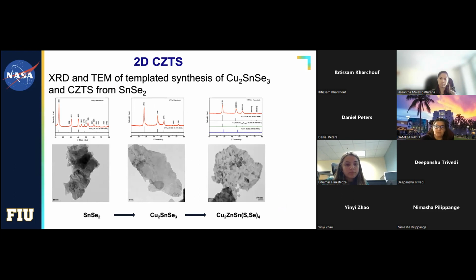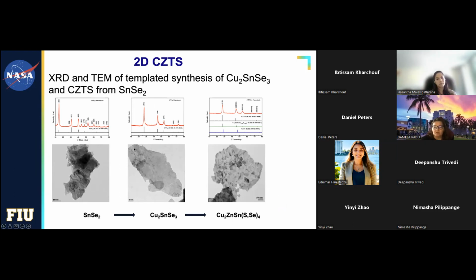And this is one paper that we recently published, where to make this copper zinc tin sulfide, we started from something that we knew forms nanosheets, not nanoparticles, which is tin selenide. And in solution, we added copper. We upgraded this to copper tin selenide, which is itself a solar material, but not as good as copper zinc tin sulfide selenide. And we added the zinc, and we obtained these nanosheets.